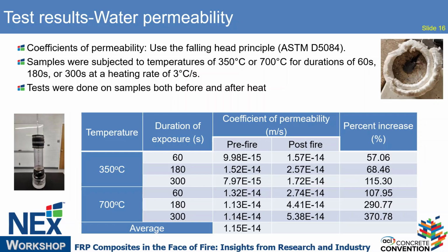And we did this for the samples before and after fire, and we found that as the temperature increased, the water permeability increased significantly. Similarly, when the duration increased from 60 seconds to 300 seconds, the water permeability also increased. For example, if the sample was exposed to 700 degrees C for 300 seconds, the water permeability increased by 370 percent.